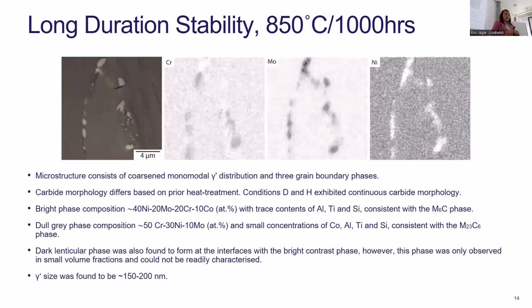We also did a quick long duration stability study that didn't really show anything. We just changed the morphology of the carbides, confirming that they stay as M6C and M23C6, nothing else. The gamma prime grew a little bit, but up to about 150 to 200 nanometers.